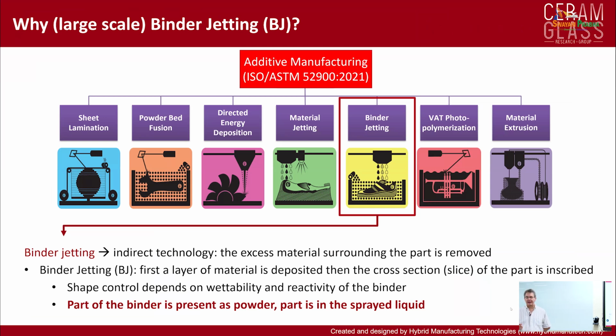If you're familiar with binder jetting, you know that the commercially available binder jetting printers use cartridges similar to the ones that you use for inkjet printing, with a resolution of about 300 dpi. But you know that the nozzles are very small and very delicate. So you certainly are not able to use alkaline solution with this type of printing head. So we own a large-scale printer that has been developed by a company in Italy, which was designed on purpose to allow for the use of alkaline reactive solution through nozzles. This printer does not use inkjet cartridges, but simply some nozzles with a certain size.